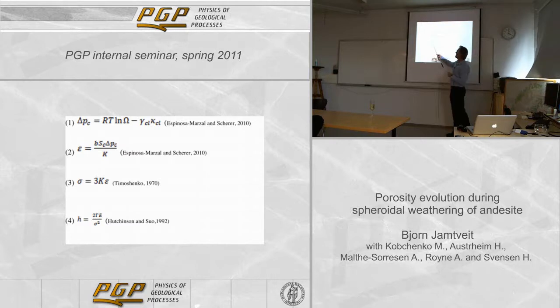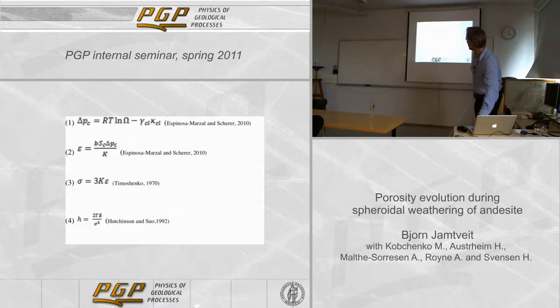And if you know the strain, then from the pressure you can estimate the supersaturation, in the case where the surface energy term can be ignored because the pores in our case are so big where things are growing that the curvature doesn't really matter. So from measuring the thickness of the layers falling, we can make a rough estimate of the pressure generated by growth in the pores. And it's quite modest.